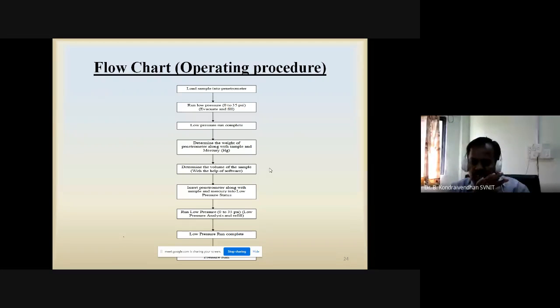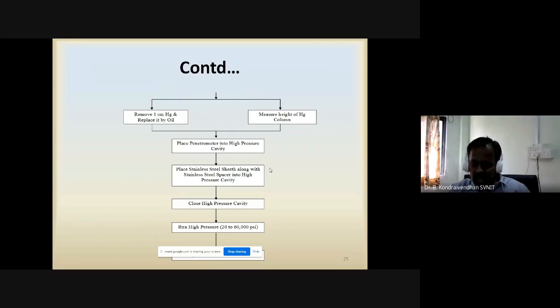Once you have completed the low pressure station analysis, then you have to put it in the high pressure station. There actually we are not using the mercury. There we are using hydraulic oil, high grade hydraulic oil. So there we are applying pressure up to 60,000 psi. There also you will get one more curve, which is also a cumulative intruded volume versus pressure curve. That's how we have to do the operation.